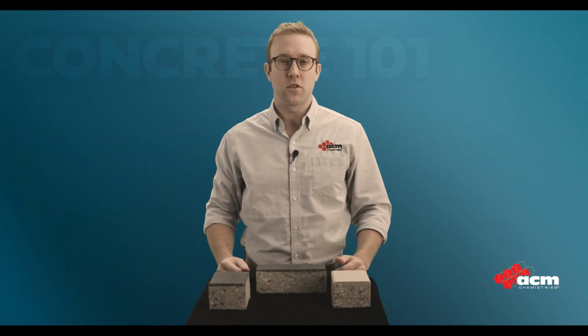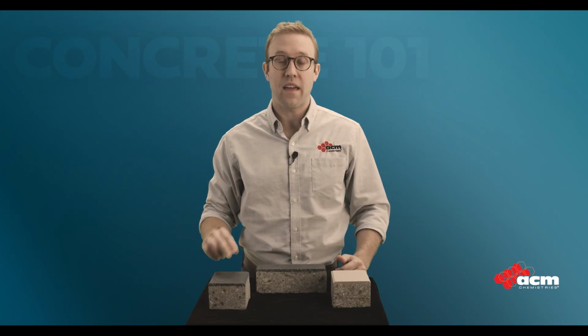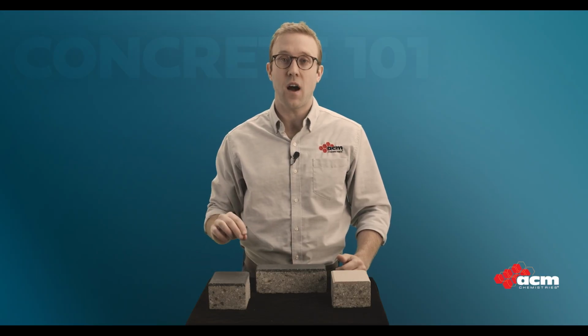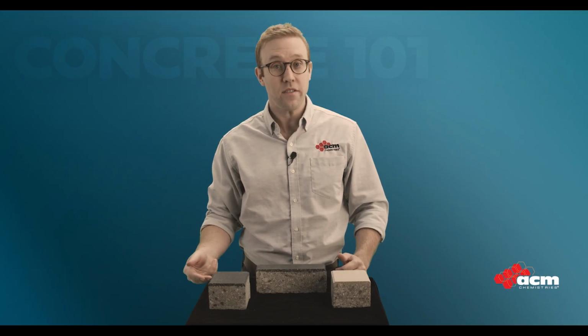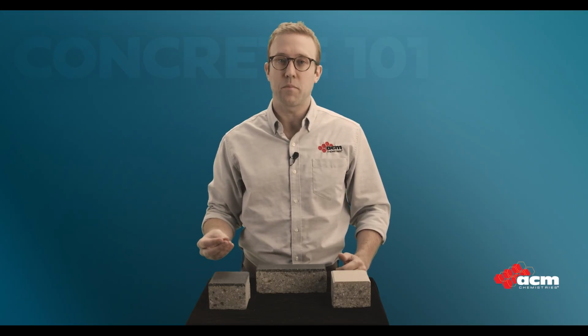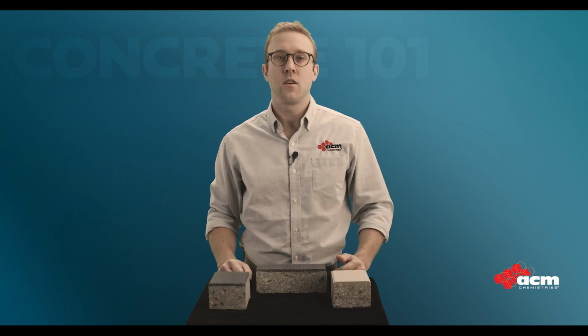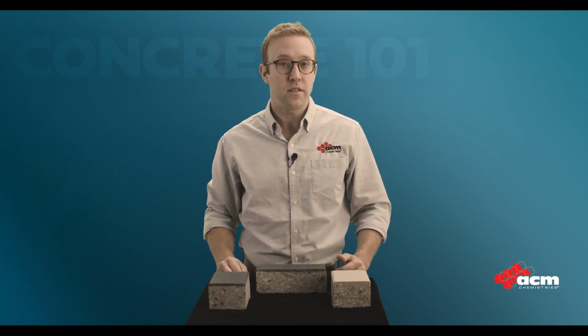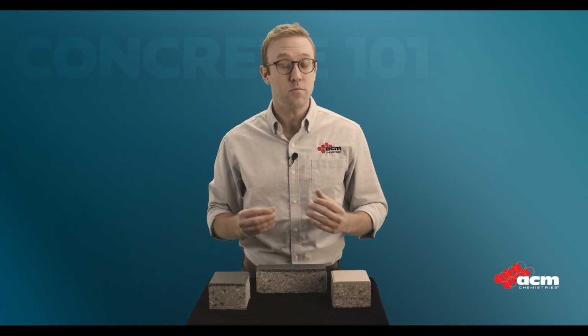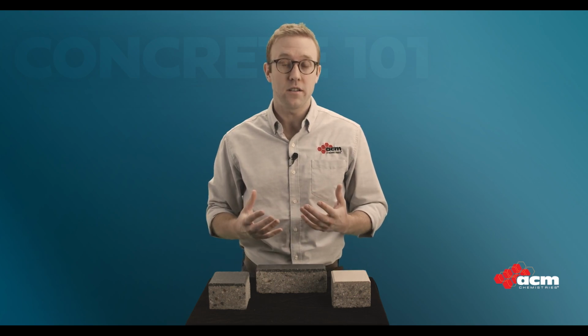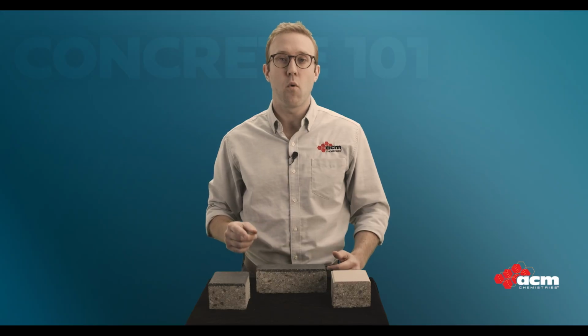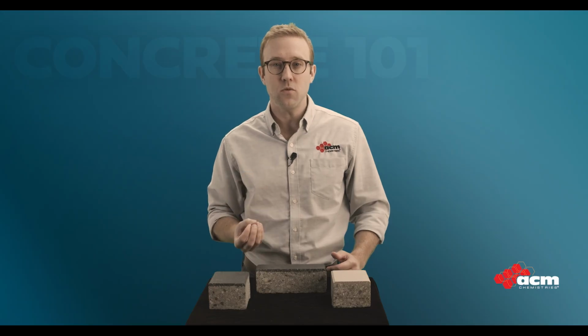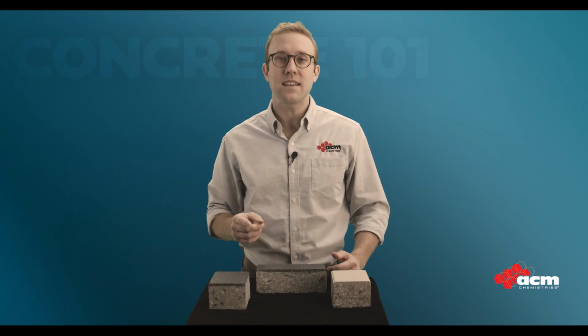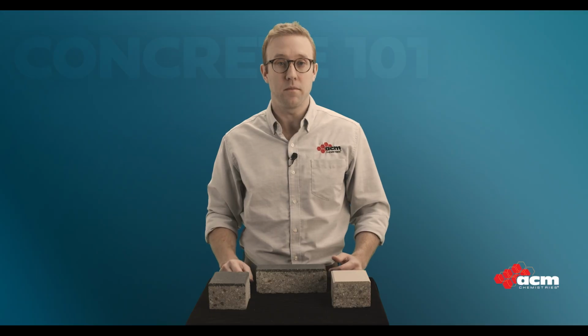So let's review what we learned about face mix. Face mix pavers have two layers. On top, a thin layer where cement, pigments, and fine aggregates are concentrated. Underneath is the base layer with coarser aggregates that provide strength and durability. When designing a face mix paver, remember that just because a face surface looks tight and smooth, the paver is not automatically better. Finer face mix designs can be more prone to efflorescence. That's due to the smaller pore structure wicking moisture into the unit. Optimized mix design and aggregate blends can prevent most of those problems.